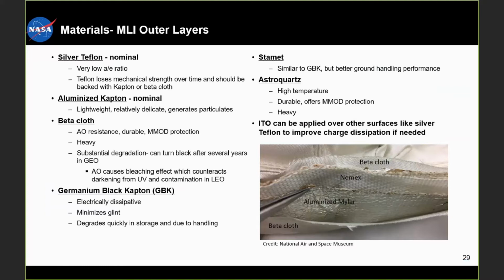So there's many different layers to the MLI. There's going to be the outer layer, separators, interior layers, as well as the inner layers. What I'm going to discuss first is the MLI outer layers. The nominal materials used are going to be silver Teflon and aluminized Kapton. Silver Teflon has a very low absorptivity to emissivity ratio, although Teflon does lose its mechanical strength over time, and it should ultimately be backed with Kapton or beta cloth. Aluminized Kapton is going to be another nominal material. It's lightweight, it's relatively delicate, and it generates particulates.